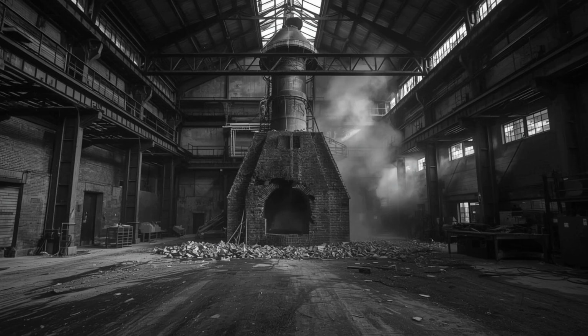But the mass was not equalizing. The lower walls were hot. The upper walls were still cold. The interior faces were expanding. The exterior faces were not. The iron bands, bolted tight, held the masonry in rigid compression. Inside the brick, forces were building silently, locked into the structure by restraint and time. The furnace was loading itself with stress that had nowhere to go.